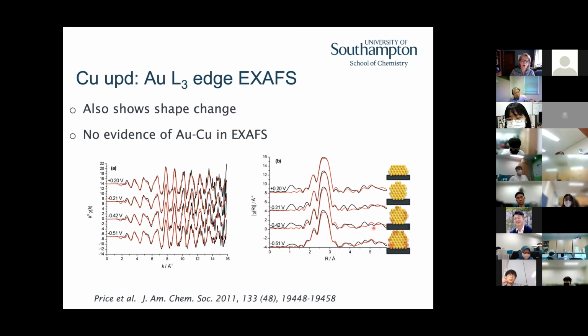What happened, just to finish this story before I launch into the proper part of my talk, is if we look from the perspective of the gold, in terms of depositing that copper on the surface, we really never see the copper in the coordination sphere of the gold. And this is because these particles are quite large. They're sort of 3 to 5 nanometer particles. And so you remember that EXAFS is a per atom average. So the average coordination environment, even when we put quite a bit of copper on the surface of these gold particles, is still that the gold just has gold neighbors, right? The fraction of the atoms that are gold that have copper neighbors on the surface is very small. And so from the perspective of the gold, we never see that the copper's there. But what we do see is that we still get the shape change in terms of particles.